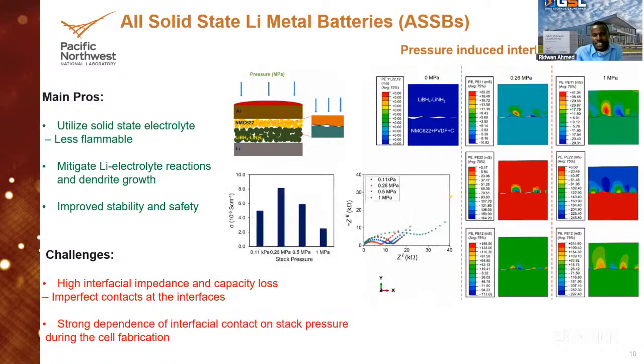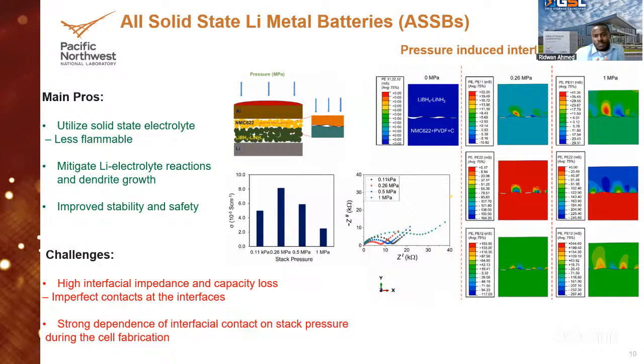So we did some electrochemical measurement just to look at the ionic conductivity. And we found out that we got the optimal or the maximum ionic conductivity when the pressure was 0.26, which is in line with what we got from the modeling, that shows that at 0.26, you can have optimal contact without inducing failure in your material. So that is one of our contributions to making sure that we have better solid state batteries.